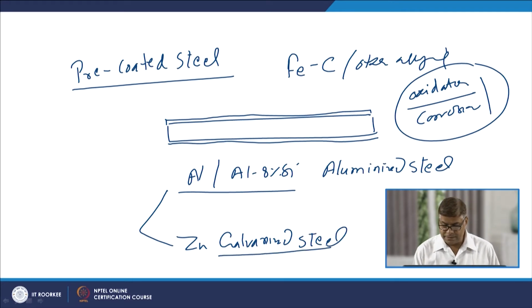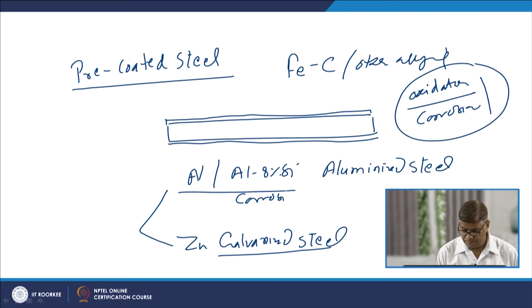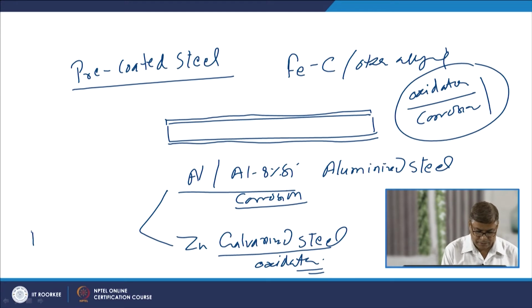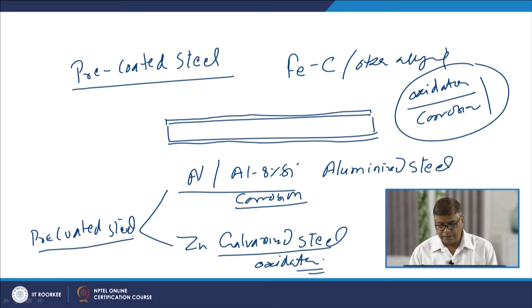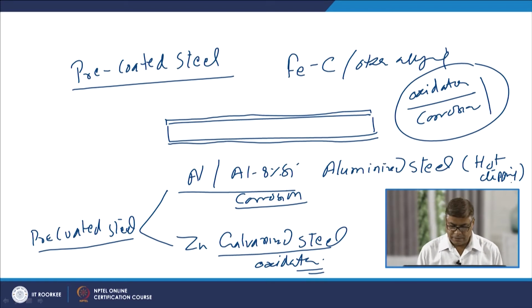So, the aluminized steels offer very good resistance to the corrosion, while resistance to the oxidation is offered by the galvanized steel. So, these are the two broad categories of the pre-coated steels. There are different methods of applying these coatings, but the most commonly used method is hot dipping. The plate or sheet or the component which is to be coated with either aluminum or zinc is dipped in the molten bath of the aluminum or the zinc and then it is taken out to develop the coating of the aluminum or the zinc.